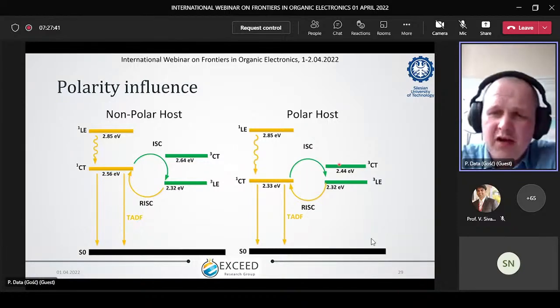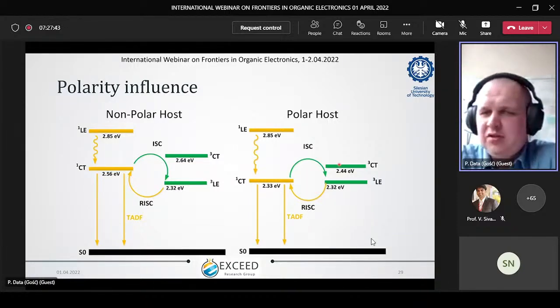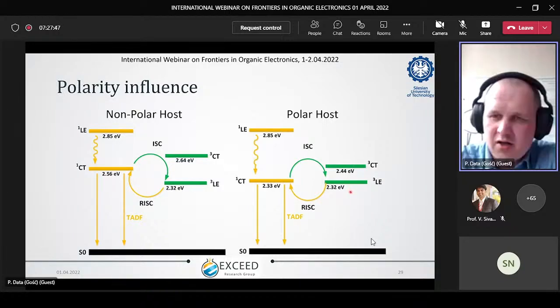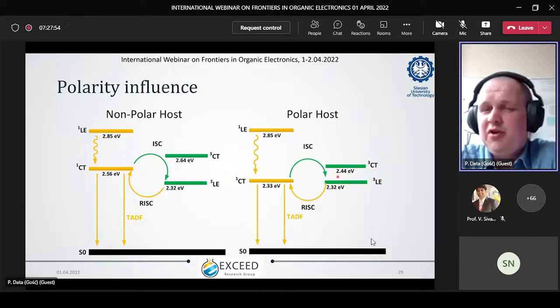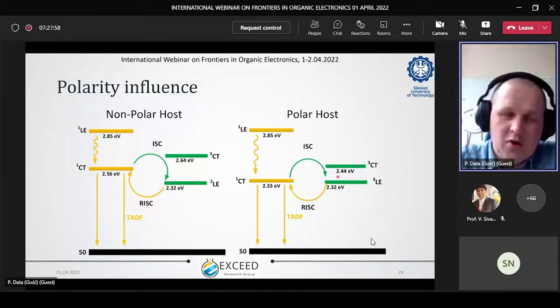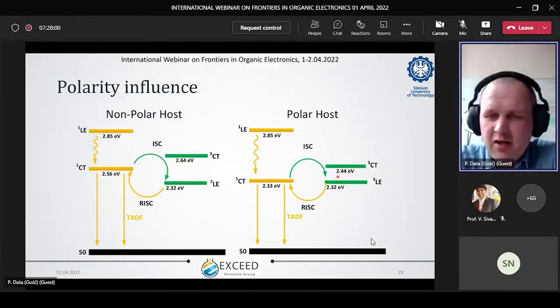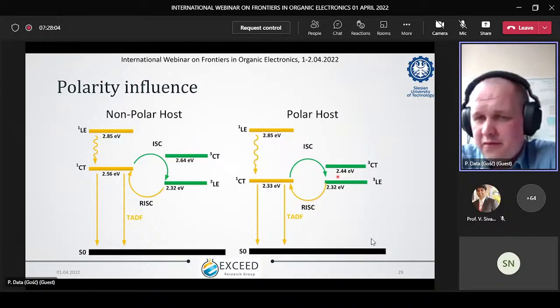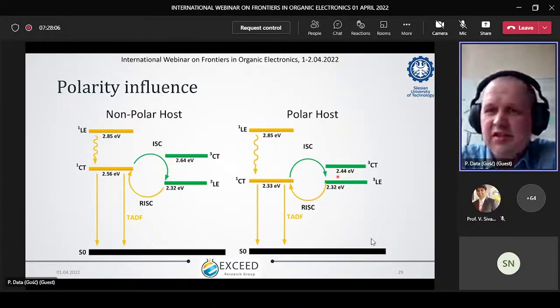And in some cases, you can find in the literature that our charge transfer state is moving below the localized excited state. And that can cause different problems, but simply you need to know that your host is always affecting your molecule. So when you are analyzing your emitter for the OLEDs, you always need to do the photophysics or the analysis in the same host which you used for the OLEDs.